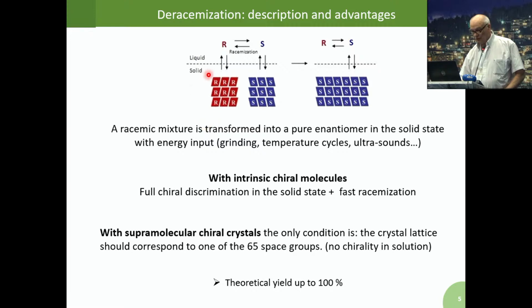It means that you have this situation here. But you don't have to care about what is happening in the liquid because here you don't have any chirality in the liquid phase. So you can apply the same process, okay? And this was actually obtained for the first time by Viedma by using sodium chlorate, which of course has no chirality in the liquid phase.